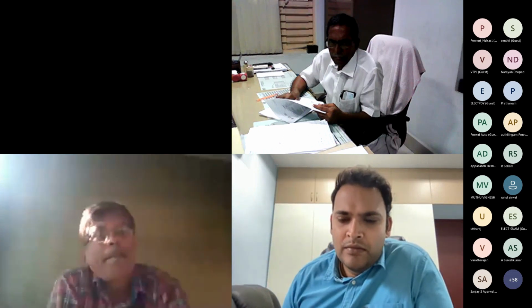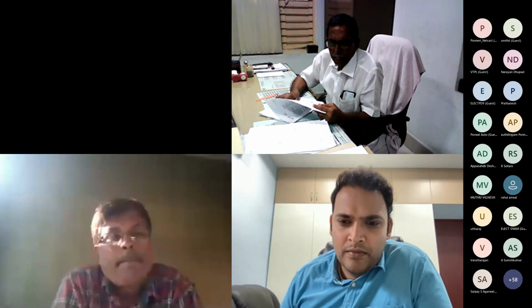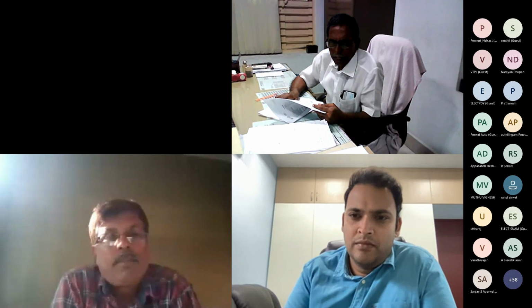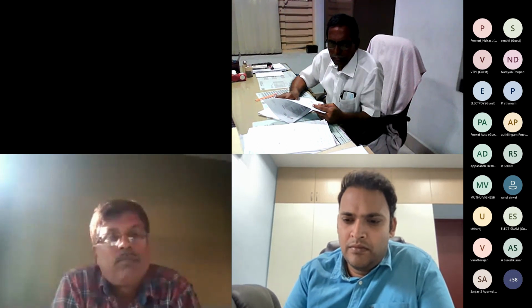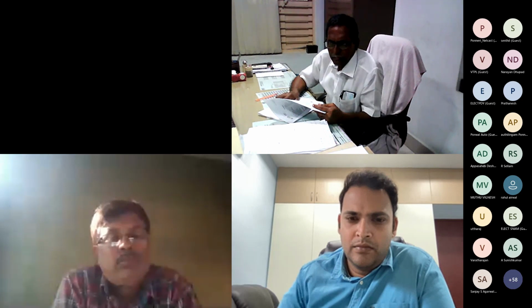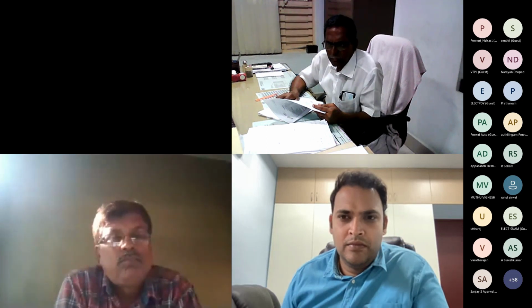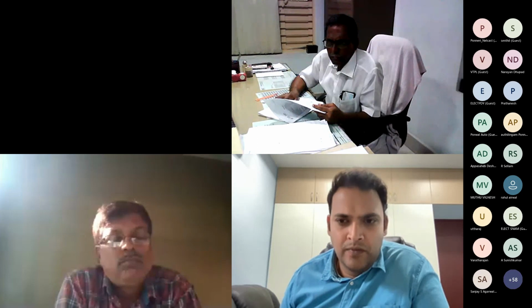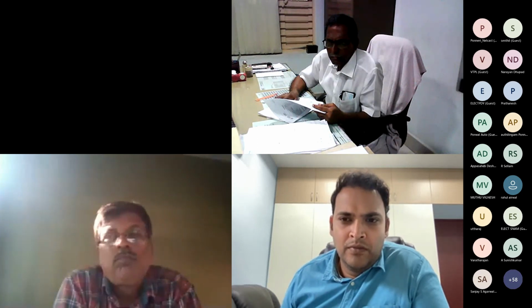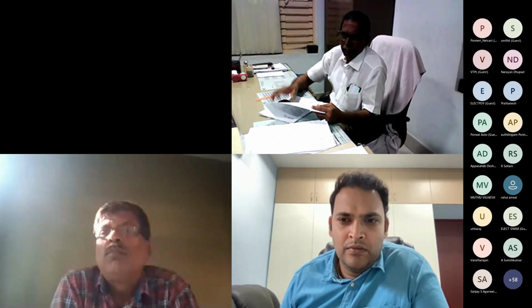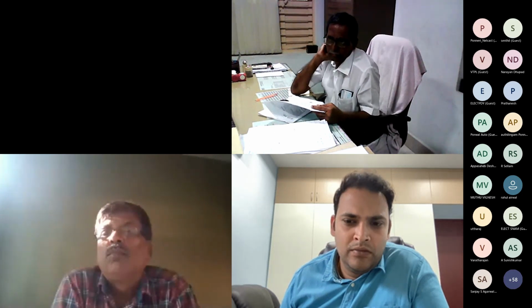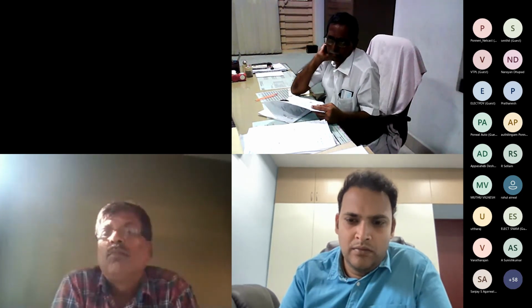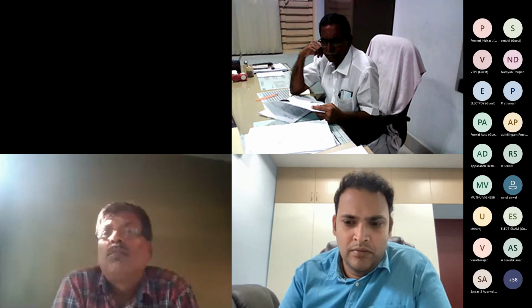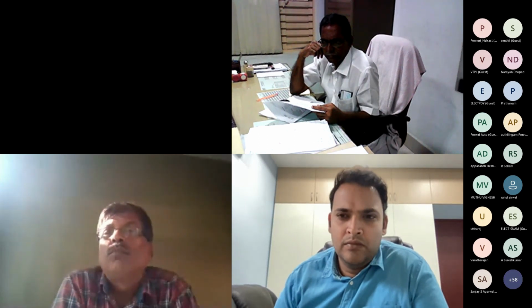So generally, according to me, the temperature difference between the cast iron and the SG is about, let's say, 50 degrees. That means the 50 degrees would require an additional 17 to 18 units of consumption. Okay. So if all the other parameters remain the same as per the U cube factor. Again, I always talk about the U cube factor. If the U cube factor remains the same, only the additional superheat of 50 degrees would consume about 17 to 18 units.